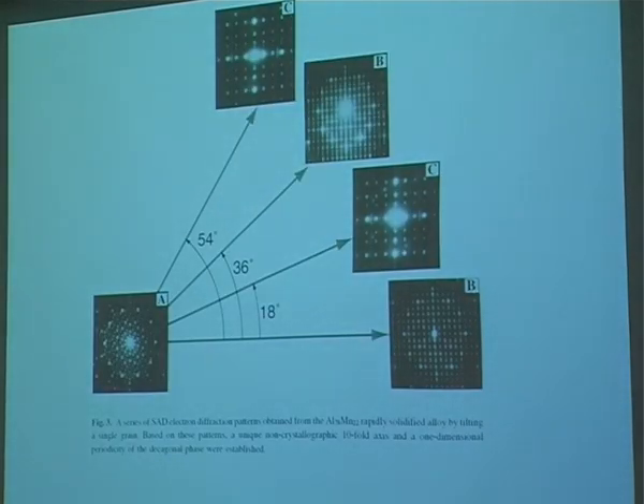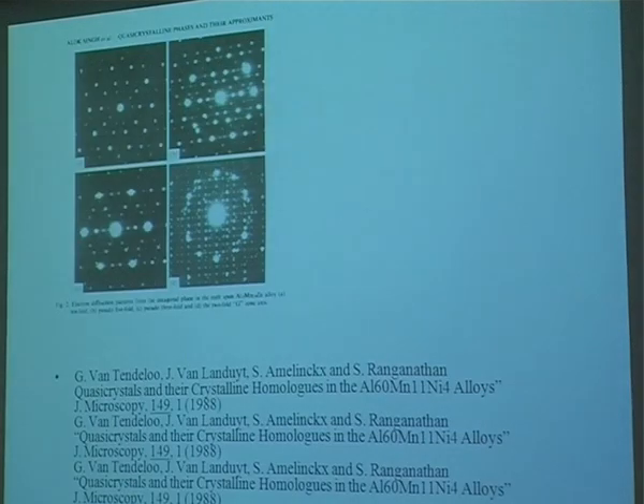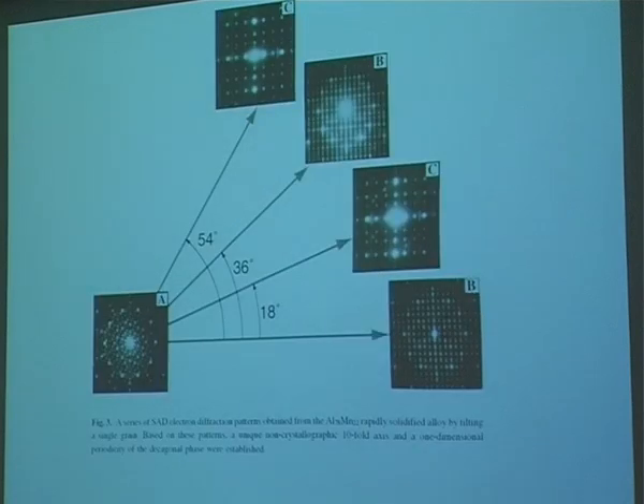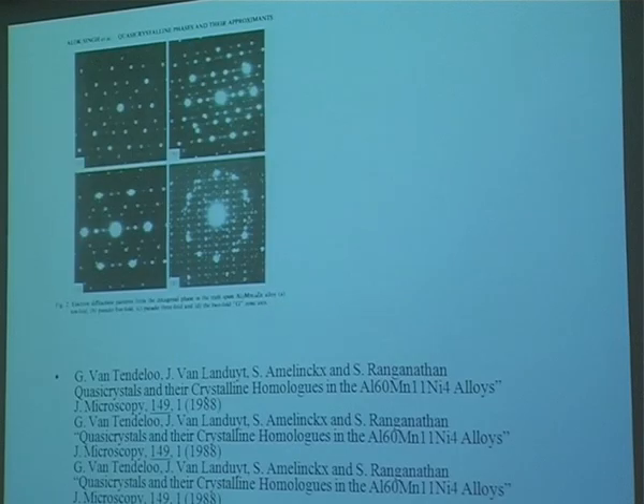This is from Louis Bendersky, who is also a student of Technion, a close colleague of Dan Schechtman, and he put together the same patterns that we had obtained, similar to that, independently, and used convergent beam electron diffraction to show that's true 10-fold symmetry, and he called it decagonal phase. So it's one of those things where the same material was looked at by two different groups, and Louis was able to spot on, find out that it's actually a 10-fold symmetry and called it a decagonal phase. But I'm very happy to share this credit with him.